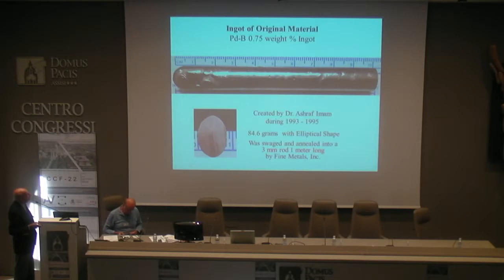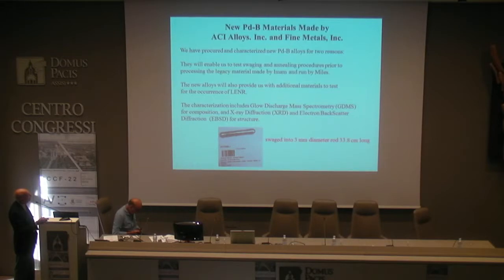This is a photograph of an ingot of the original material that we recently had swaged into a 3 millimeter rod, a meter long, by this company in Virginia. So we now have a substantial amount of the original material. We had a company make another ingot of the material, which is shown here, and it was swaged into a 3 millimeter diameter rod, about a third of a meter long. So we have a substantial amount of both the old, the historic, and the new materials.